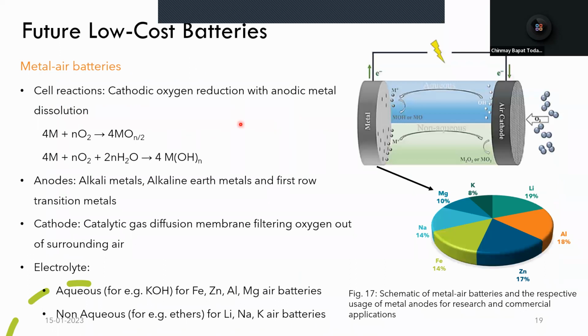Towards the end, we have metal air batteries, which have a higher energy density as compared to lithium-ion batteries due to the use of metals such as aluminium, zinc, etc. For the reactions, we have cathodic oxygen reduction at the cathode and anodic metal dissolution at the anode. That is, the metals get oxidized and they form metal oxides, and these metal oxides lead to the exhaustion of the metal anode. So when the metal anode gets exhausted in the form of metal oxides, we can simply remove the anode and replace it with a fresh metal, and we can run our cell again.